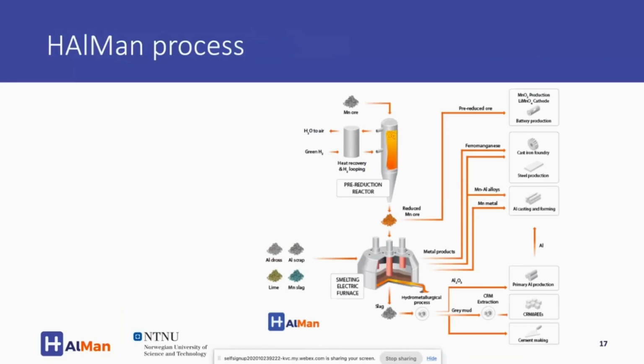The slag, as Professor Jafar mentioned, is this calcium alumina rich slag. We extract alumina and evaluate if we can take it back as a raw material into the aluminium process. And what we also do, the gray mud is evaluated in the cement industry, but we also extract critical raw materials from this gray mud. So we really try to extract all valuable elements from the input materials. And the aim is to have a near to zero waste process. So we utilize all streams and then also a CO2-free process.